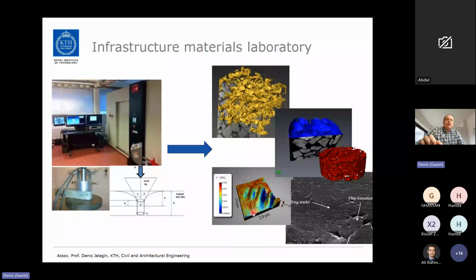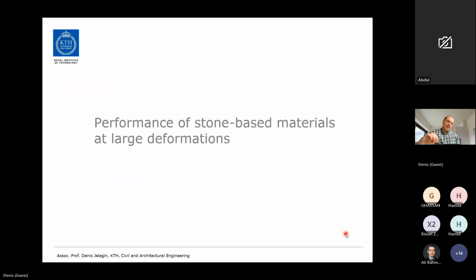And also we developed our own contraption to test contact-induced deformations and damage in stone materials. One cannot see, but underneath this big cylinder, we have a small spherical indenter, which is pressed into the stone specimen, and then we measure deformation and damage accumulation in the material. So we can see formation of ring cracks in the material. This is an SEM picture. Here we have a group of ring cracks, and here we have chip formation in stone material, which allows us to gain better physics-based understanding of how stones deform, wear, and break due to contact loads. So that was our group in a nutshell.